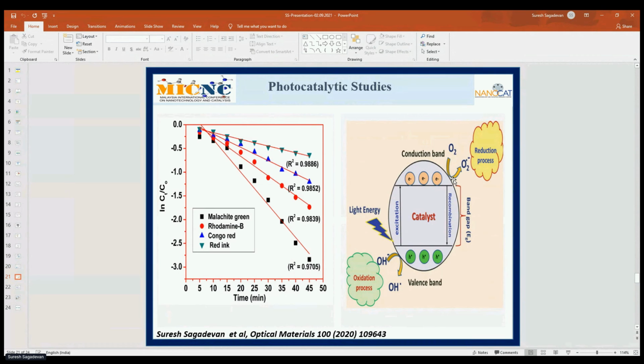So this is a schematic diagram for this composite. From this graph, after receiving the visible light, electron-hole separation occurs simultaneously on the composite. The electron moves to the conduction band, leaving the holes, H plus, in the valence band. This process significantly reduces the electron-hole recombination occurring in this composite. The electron in the conduction band of the catalyst gets trapped easily by the surface adsorbed molecular